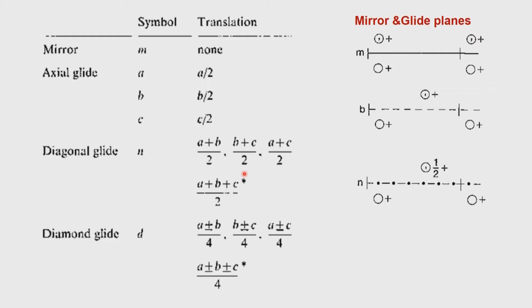The glides can be along all three directions, because your definition of the glide plane is only with respect to half translations, and your A, B and C are not necessarily the axis in case of the rhombohedral and the cubic systems. There is another thing called the diamond glide, which will occur in tetragonal systems, and this could again have a 1/4 translation, combining both A and B directions.